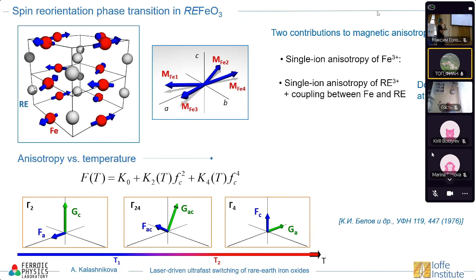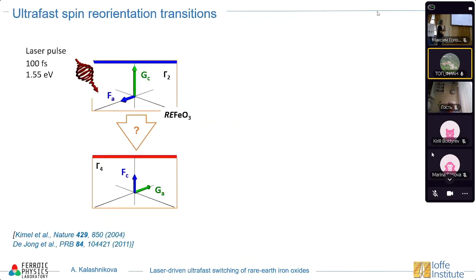Because at low temperature, magnetic moments of rare earth ions are large, therefore this contribution dominates. And actually, this also explains the fact that these temperatures are really strongly dependent on the rare earth type itself. So, in principle, if we heat up this material, we can really switch magnetization from one phase to another phase. Is it possible to do it by a femtosecond laser pulse? Yes, of course. If there is absorption, there will be heating. And in principle, we should be able to go from one phase to another one. It was first demonstrated in 2004 by our colleagues from Nijmegen and also by Roman Pisarev.